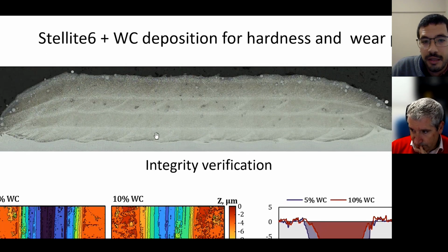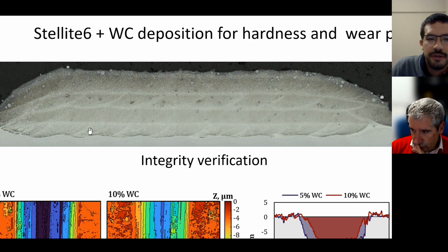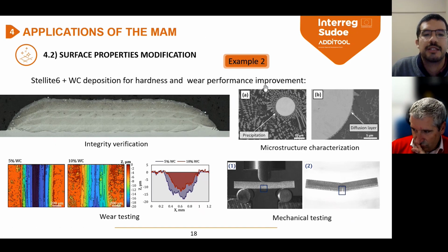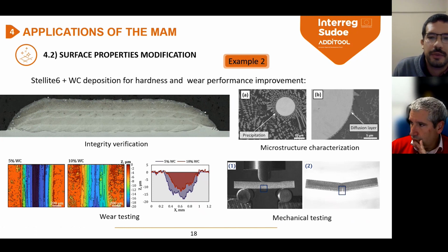In this case, this test was performed using the FGM strategy because we vary the composition of each layer. First of all, we start adding only Stellite 6. Then we introduce also 5% tungsten carbide, 10%, and in the last layer, we can go up to 50% tungsten carbide and obviously 50% of Stellite 6. That way, we avoid crack problems and we increase the resistance of the coating.